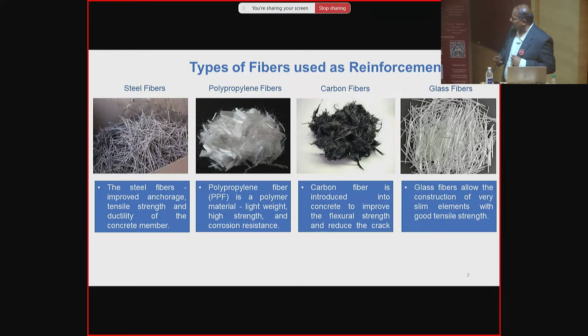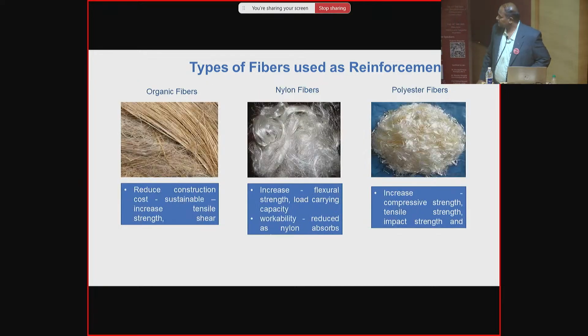So carbon fibers are also used. Glass fibers are basically made from silica sand, which is heated to around 2200 to 2300 degrees centigrade, and it is in a molten form. It is made into a fiber using the fiberization technique, right? So organic fibers, nylon fibers, polyester fibers, all are there.